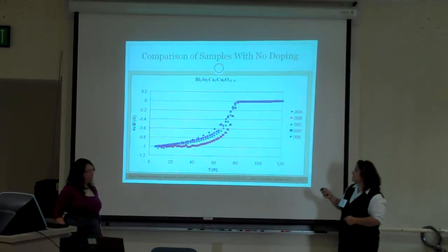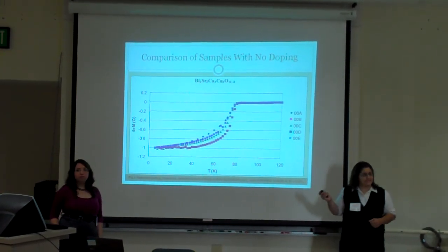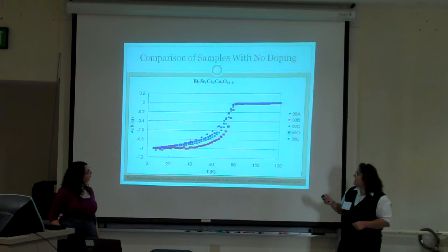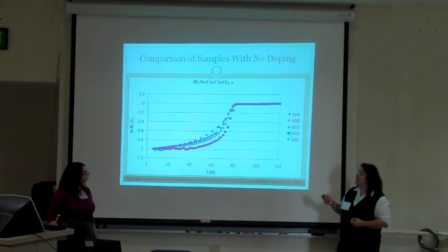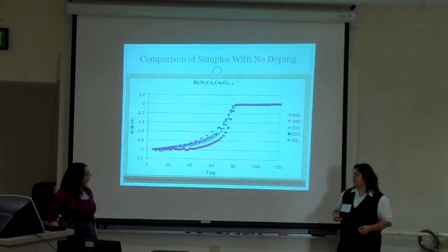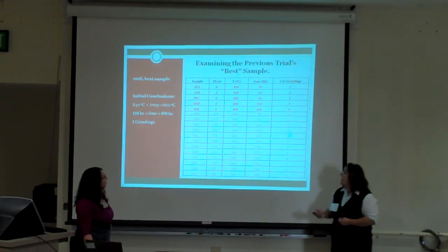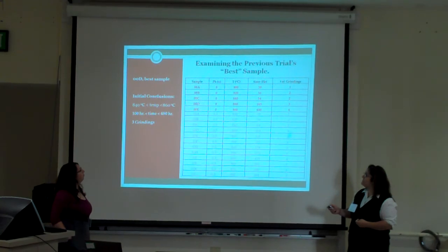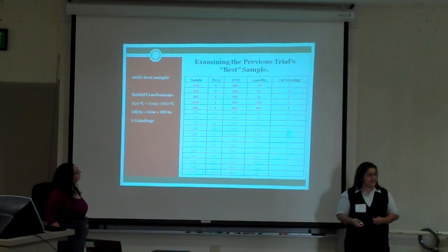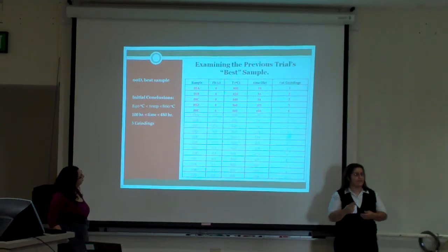But what this graph also shows is that changing the temperature and the annealing time does seem to have an effect. From this graph, we can see that sample D is the best sample in that it has a high TC onset, a steep curve, and a relatively stable tail. Those are the three properties we are going to be looking at in all of these graphs. The difference between sample D and all of the other samples is that it was heated to 860 degrees Celsius, allowed to anneal for 103 hours, and utilized 3 grindings.